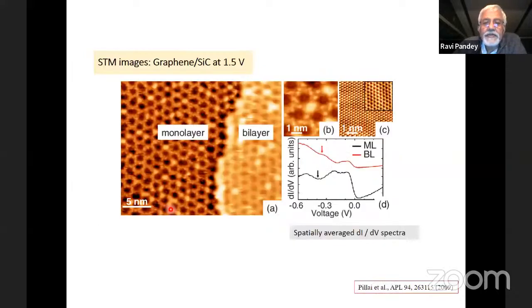This image shows the STM, where graphene is deposited on silicon carbide. At a certain bias, you can really visualize the monolayer of graphene, with the nice hexagons formed by the carbon rings. If you go further down, you have the bilayer, and you can characterize it by looking at the conductivity, the derivative of current with respect to voltage. You can see nicely this curve represents the monolayer, and this curve represents the bilayer of graphene. So you can really distinguish between a monolayer, a bilayer and further multi-layer compounds using these beautiful imaging techniques.